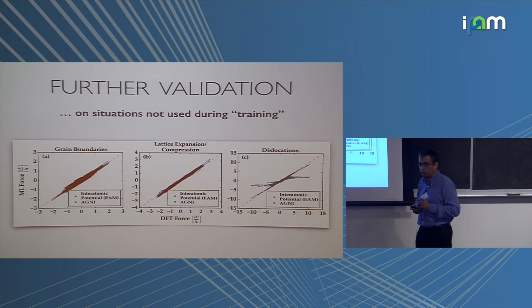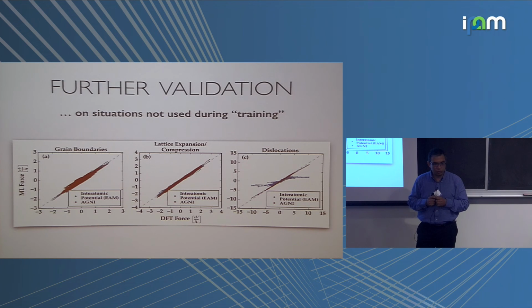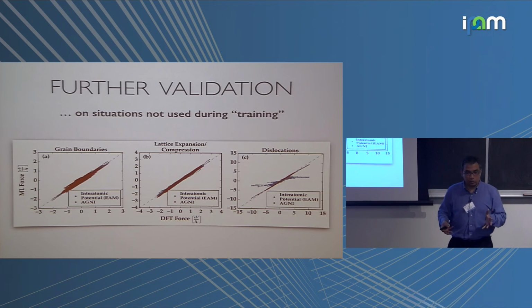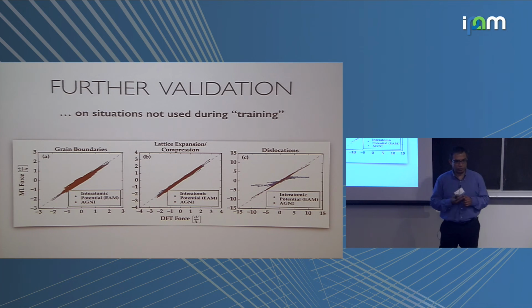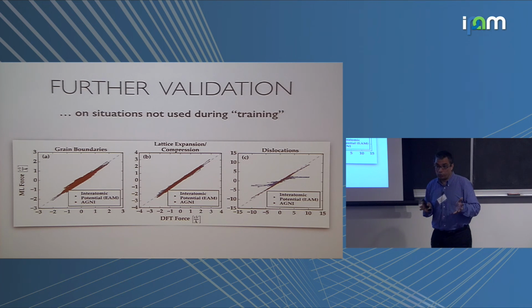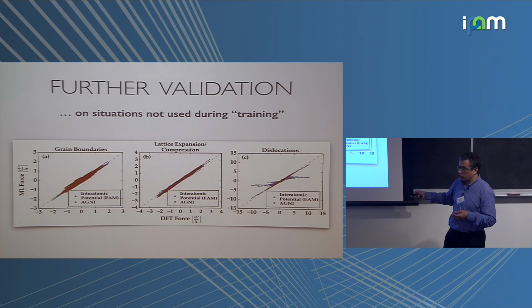we created an edge dislocation in aluminum, a rather large calculation, and perturbed the atoms around the dislocation core and everywhere. We computed the forces using DFT, computed the forces using machine learning, and that's the red plot. As you go to larger and larger forces, plus or minus, there is some deviation, but it's relatively small. But if you look at EAM, which is the blue stuff, it fails. Embedded atom method and many classical force fields are built from equilibrium sort of situations, and so if you stray far away from equilibrium, they are prone to fail. And I think DeVita's group has recently also come up with the same sort of conclusion based on comparison between embedded atom method and DFT for dislocations as well. So that's kind of what we are seeing over here.